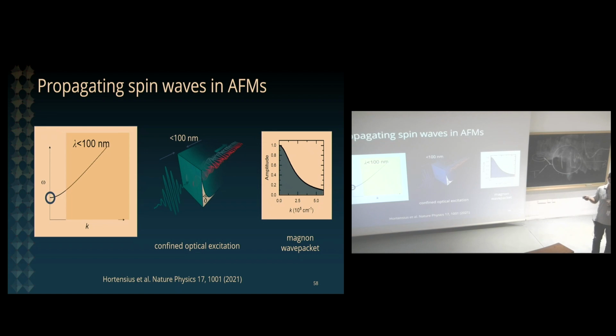However, after doing a lot of experiments with resonances, we realized something that we found quite interesting. The idea is the following: if you can find a resonant mode that has a penetration depth that is way below the wavelength of a specific excitation that you're interested in, then you have a chance of confining your excitations over a very thin skin depth inside the material, and this can provide a certain number of Fourier components to a propagating wave packet.